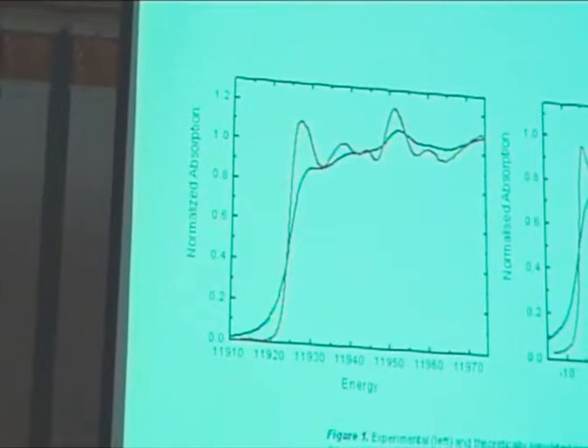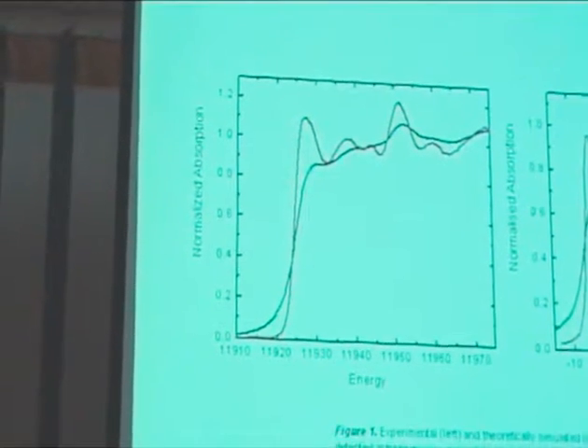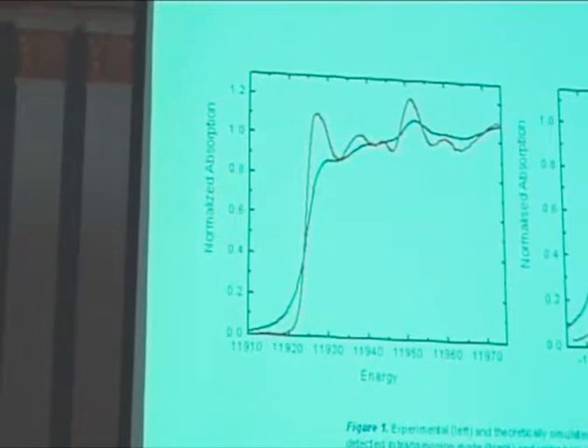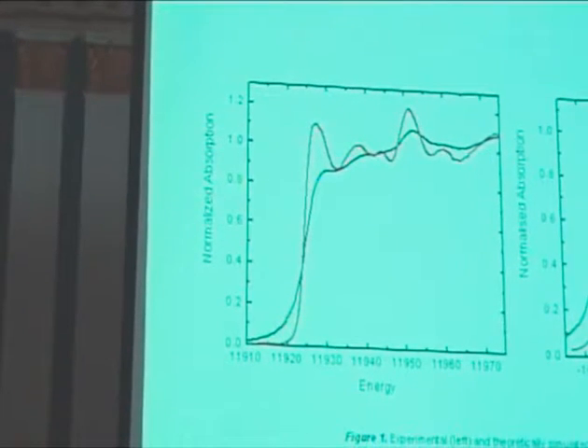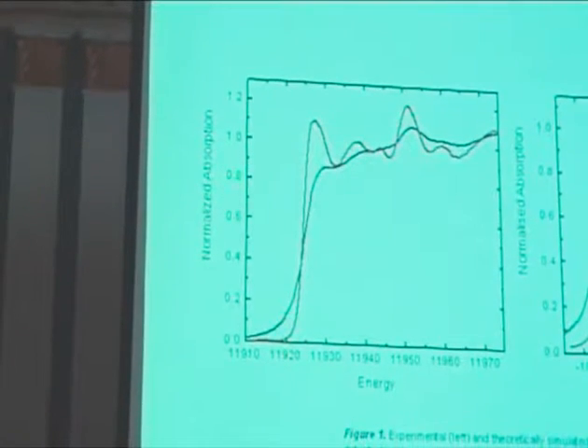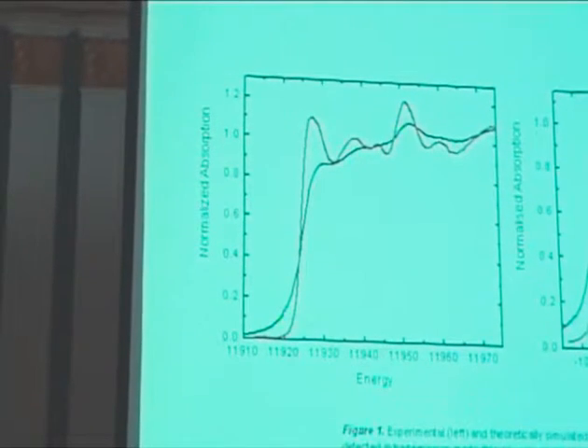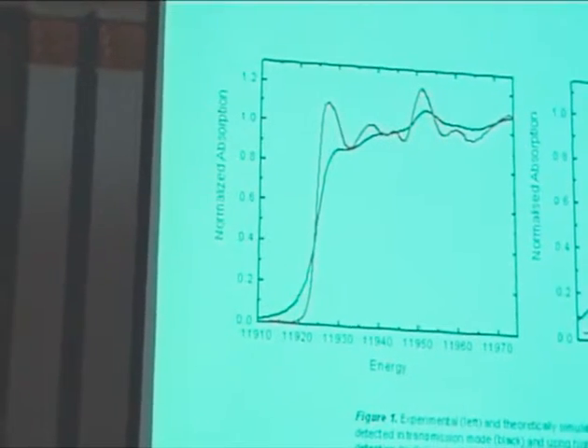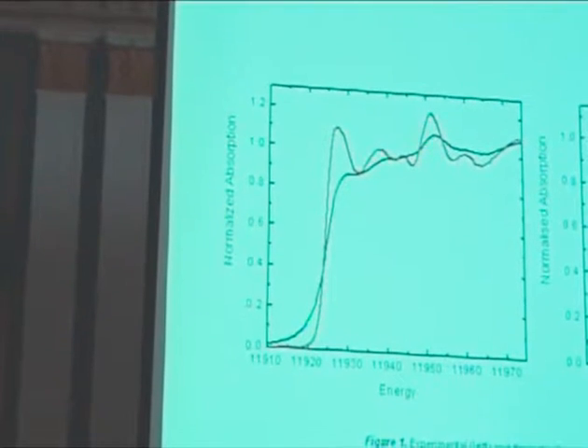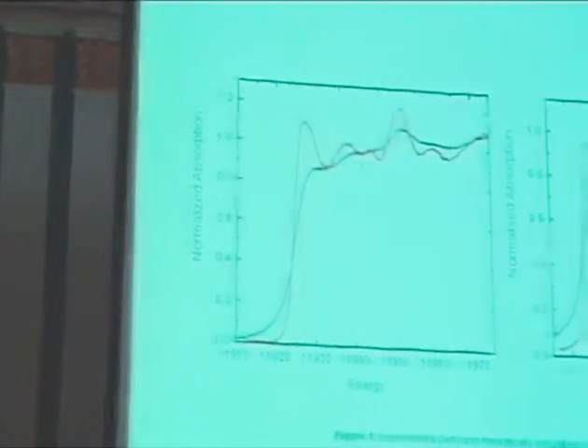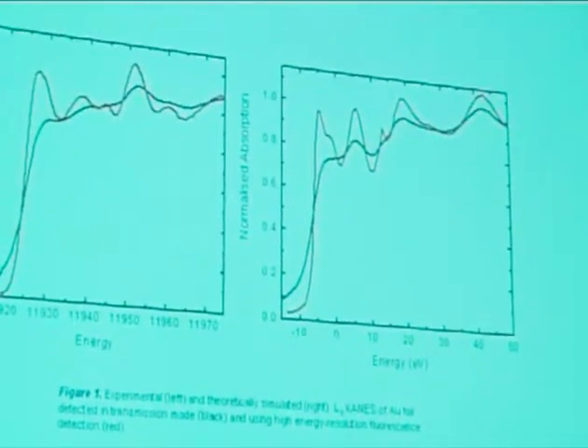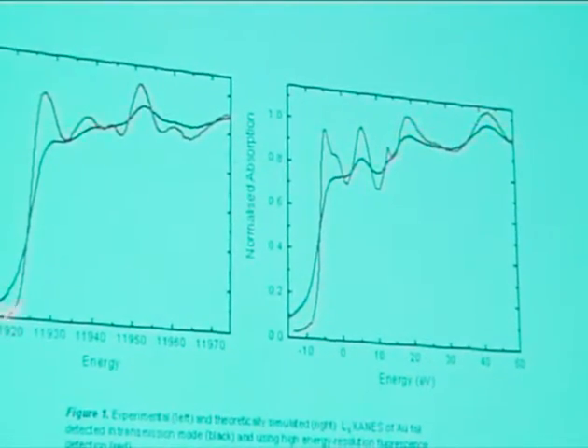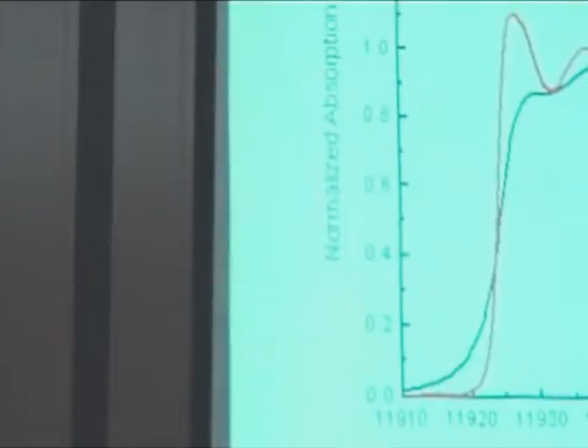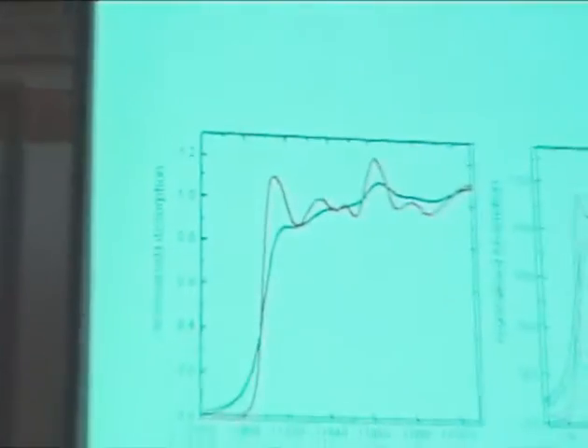And we had always thought, why isn't there a little bit of a d hole? Because you have the d band and the s band, and when you have the hybridization, it's like a water reservoir, the empty holes in the s band, so you can pump electrons from the d band into the s band, so you free holes in the d band, so you must have some intensity there. And why was there nothing? The answer is there is something. Look at the red curve. What is the red curve? It's the same gold foil, but now measured with a different analyzer.